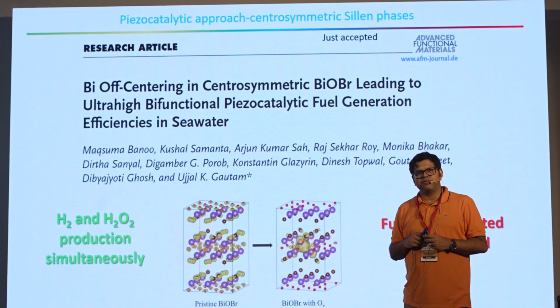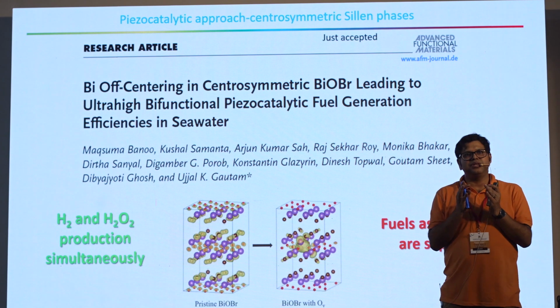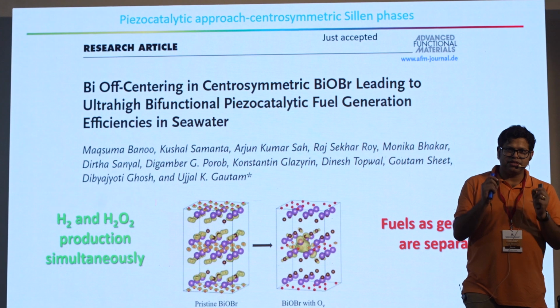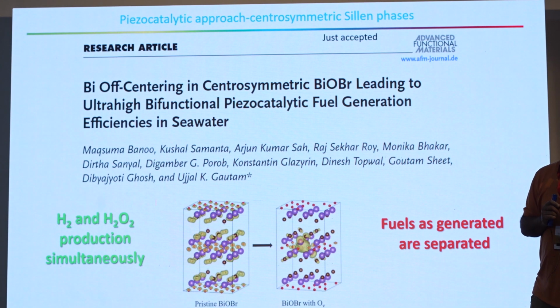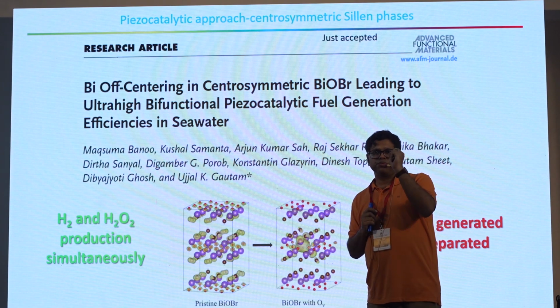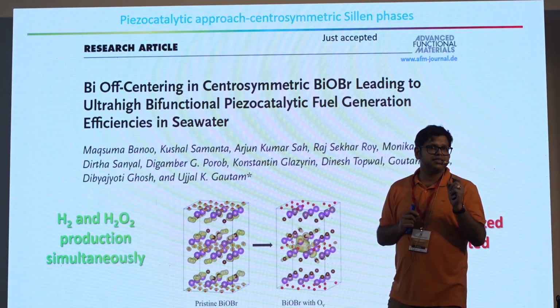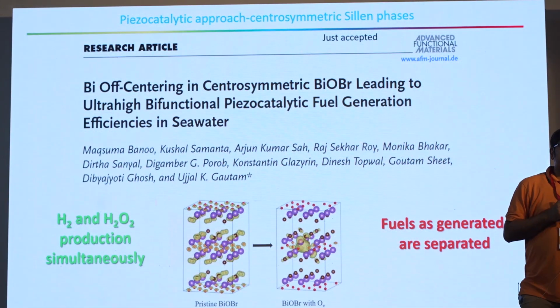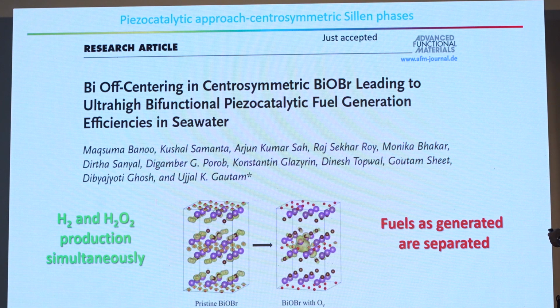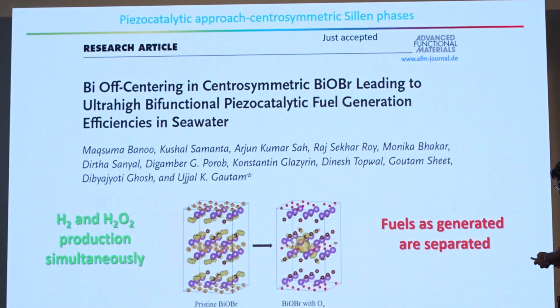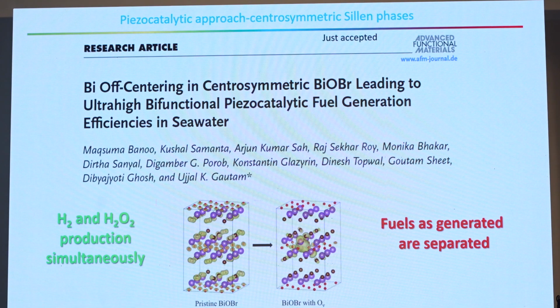So the last slide I'm going to show about piezocatalysis is that I just mentioned that we have to use a non-centrosymmetric system. But the majority of the materials that we have are not heavily non-centrosymmetric. They're not heavily polar. So if we can use non-polar systems and still do piezocatalysis, this is excellent. And if we want to do this, we somehow have to introduce non-centrosymmetry in the system. So in this case, it is about introducing vacancies within a centrosymmetric crystal. This is a BiOBr crystal. I'll come to what BiOBr is. When you introduce oxygen vacancies, these unit cells become polar. So you can control the amount of vacancy and generate a large amount of green hydrogen.